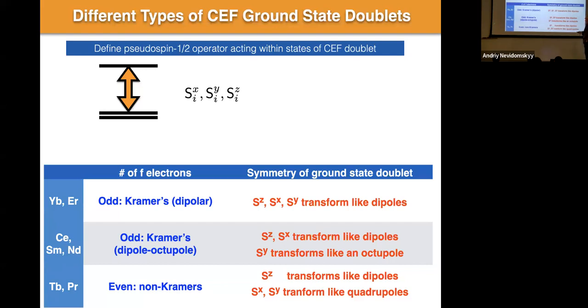So it turns out that for all of these rare earth-based insulating pyrochlores, you get the same sort of phenomenology in that you've got some relatively large total angular momentum for the rare earth site, but there's 2 states which are pulled down below everything else, and at low temperatures you can forget everything else. So you end up with a pseudo spin a half degree of freedom associated with those 2 states. And then it turns out that you can classify the nature of the doublets that you get across this rare earth series, okay? And you classify them on the basis of the symmetry of their wave functions. And they break up into 3 groups.